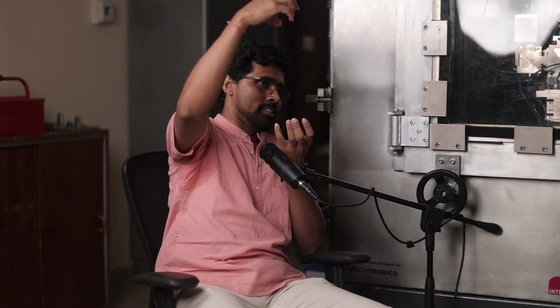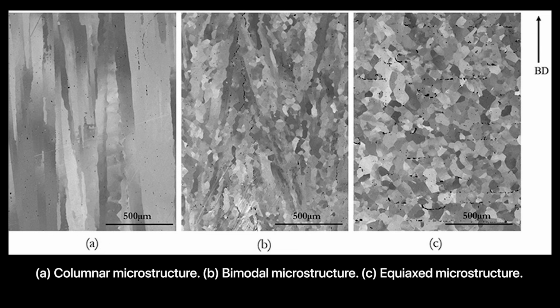Then the second part was they realized that most of the loading is happening radially. If you have a blade, it's only loading in the radial direction. So if we do not have any grains which are perpendicular to it, that would also improve the life. So the process evolved to making a columnar microstructure, where you will have grains, but most of those grains would be single from bottom till the top. So that was one thing.